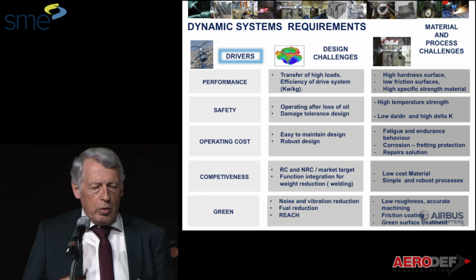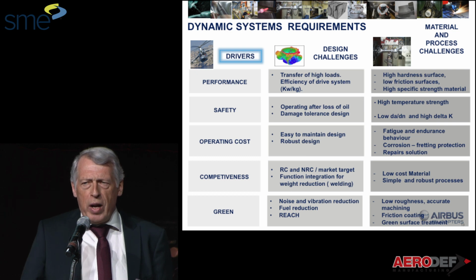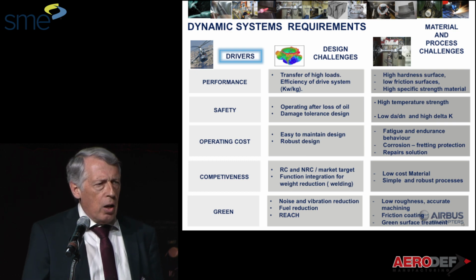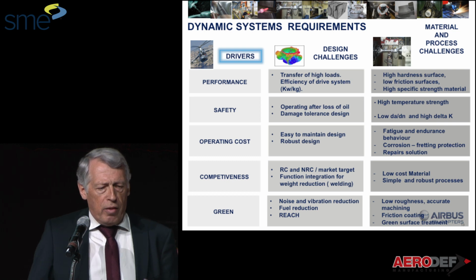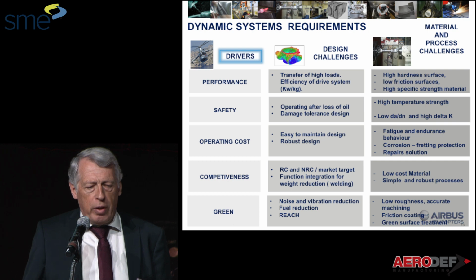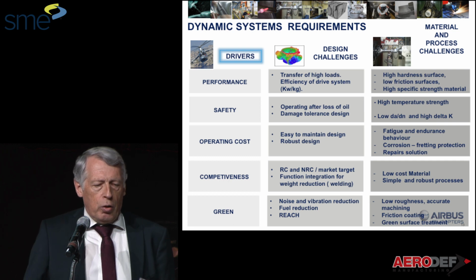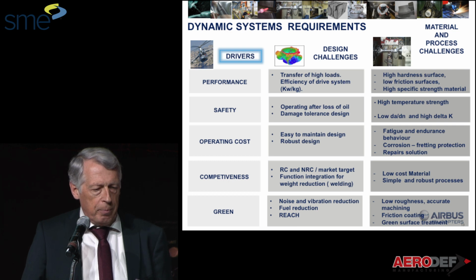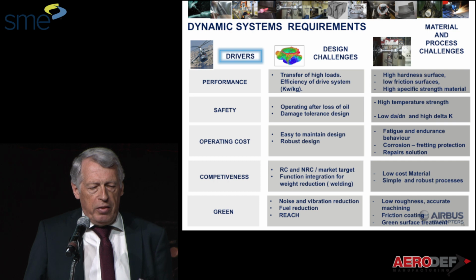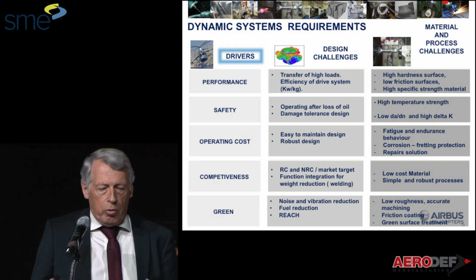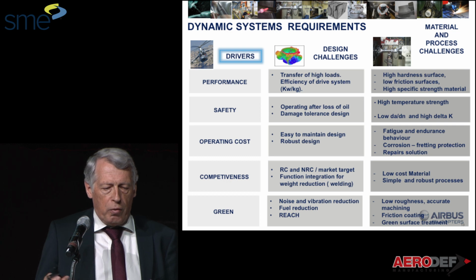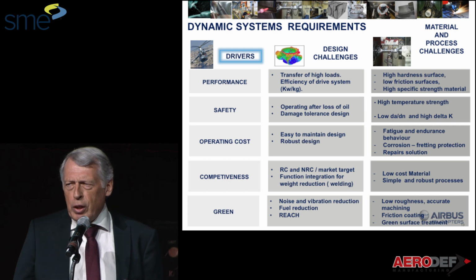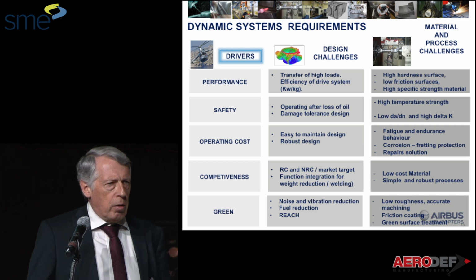For safety, we have some constraints concerning operating after oil loss. We have to prove that the helicopter is able to fly after oil loss. We also have to prove that we have a damage tolerant design. That means an impact on the high temperature strength, which is part of the qualification, and also on the crack propagation and delta K for the initiation of cracks. Operating cost means easy to maintain design, robust design. So there is also an impact on the material and process for fatigue, endurance, corrosion, and also to include in the design whether the part will be repairable or not.